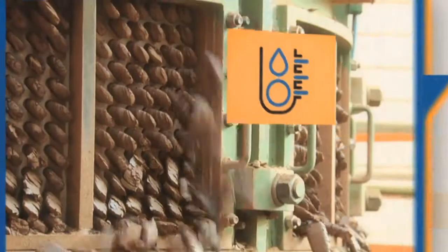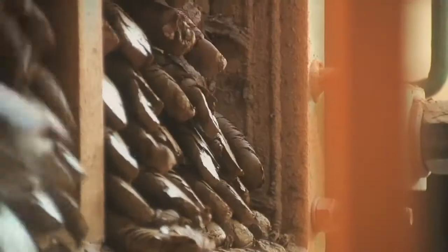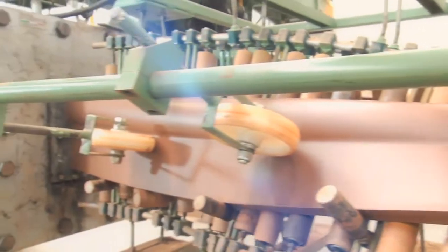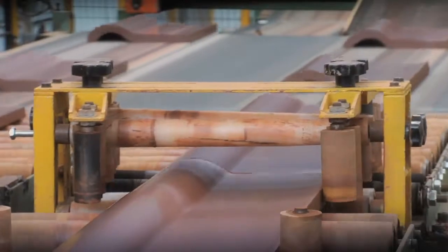Following a process of homogenization, the moisture levels of the mixture are readjusted in the extruder, and the air is removed in a vacuum chamber, thereby obtaining a compact flow with the pre-mold of the tile, which is cut into fragments of the right size, which are subsequently molded into what we call biscuits.